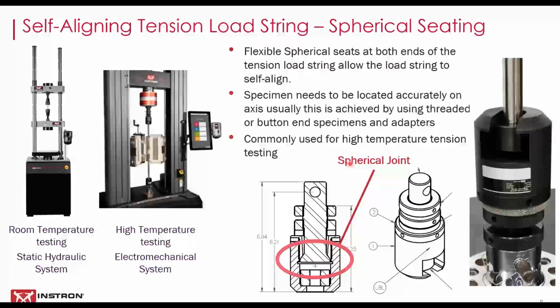If we look at the self-aligning load string in a little more detail, here's a couple of examples. Here's a room temperature example on a small static hydraulic system. This approach is not particularly dependent on the characteristics of the testing machine, since you're allowing the string to self-align. In this case, the universal joints have spherical joints, and this is the detail of the spherical joint. This would be up at the top of the machine here, and there'd be a similar one at the bottom.